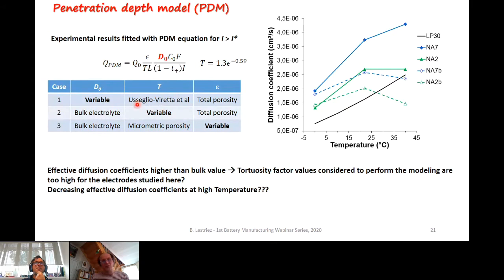Here I'm showing the results where we consider the lower bound of Usseglio-Viretta. So here are plotted the effective diffusion coefficients, the values extracted from the fit, as a function of the temperature for the various electrodes, and compared to the bulk lithium diffusion coefficient. So first, we were happy to see that we obtain good order of values for the diffusion coefficients, and we reproduce the temperature dependence to some extent, except for some electrodes. I'll be back to that later.